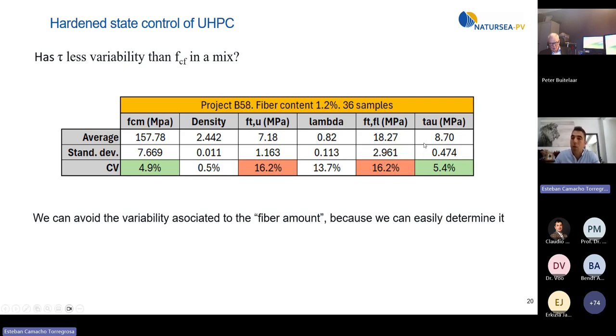However, after doing the procedure, the variability of the bonding strength tau is only 5.4%. So it is almost as constant as the compressive strength, because in the end it's intrinsic, it is associated to the matrix and to the type of steel that we use in the fiber. So as we can determine the fiber amount that we have in the beam, we can avoid this variability.